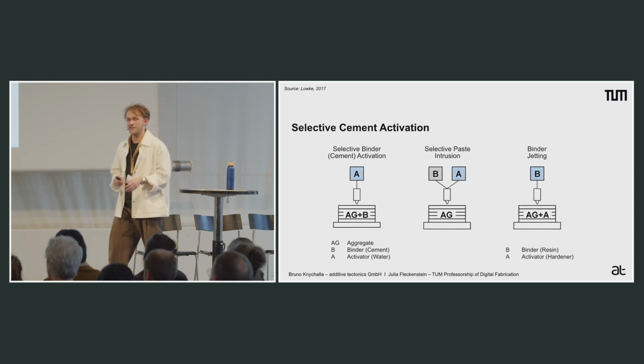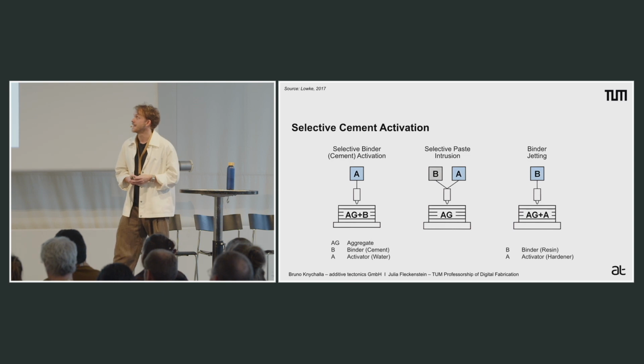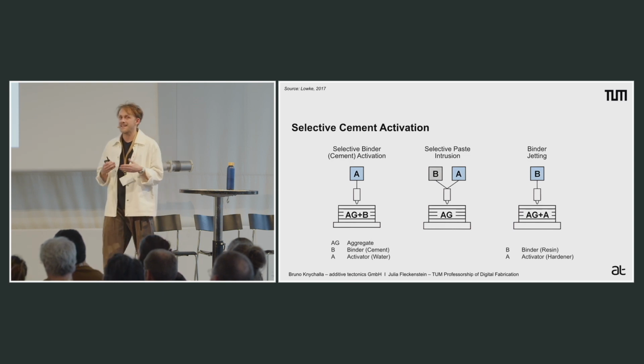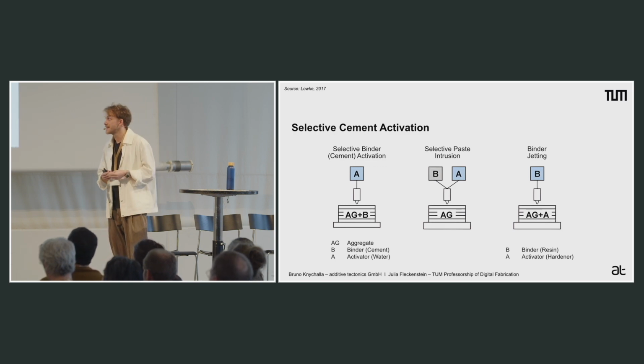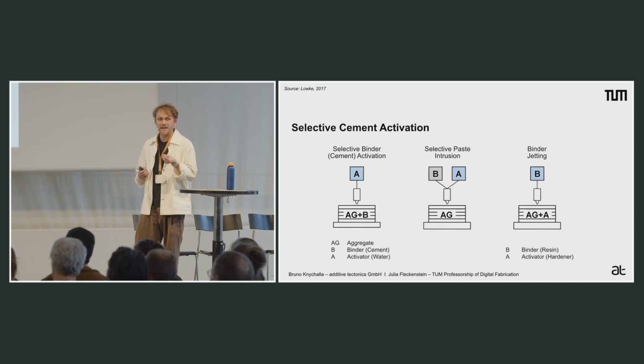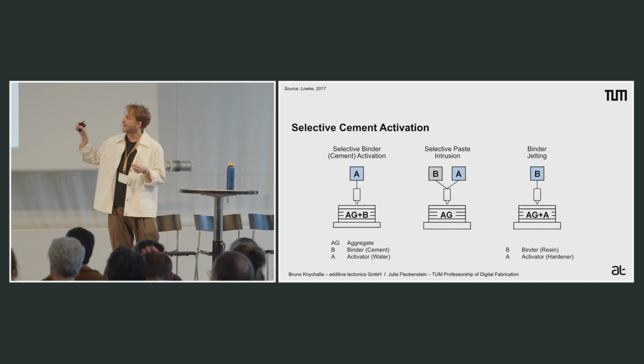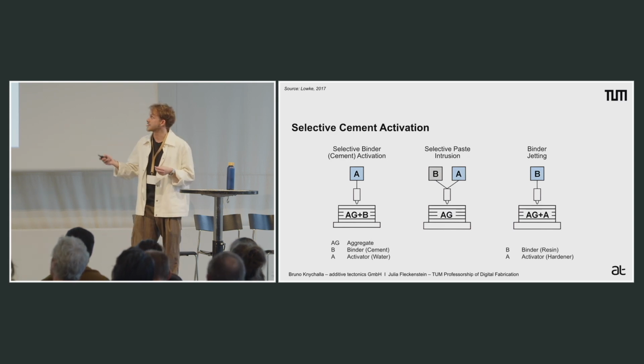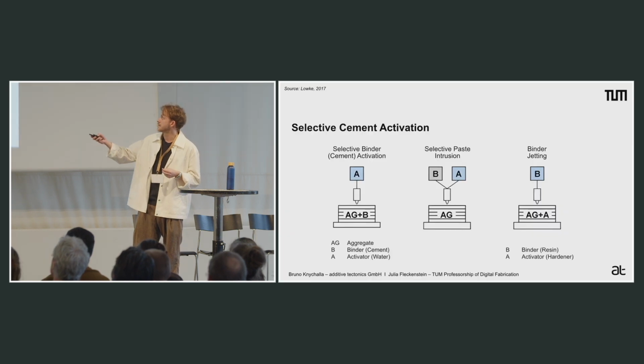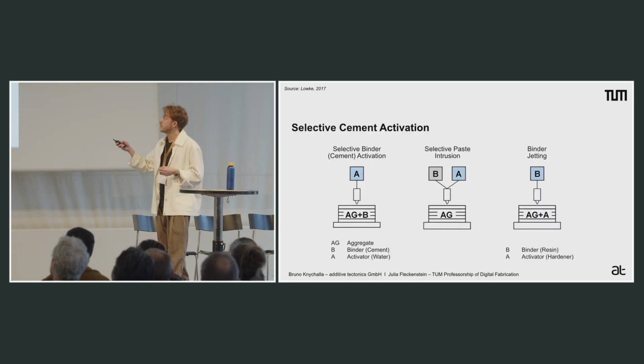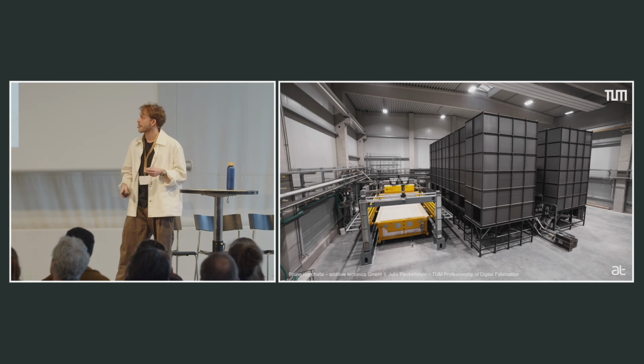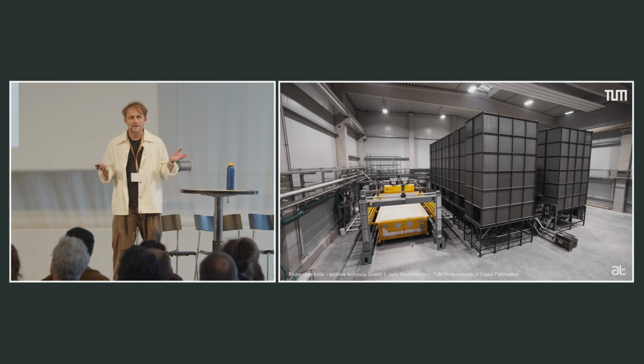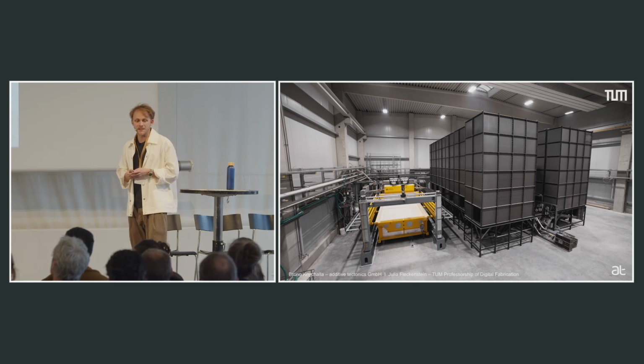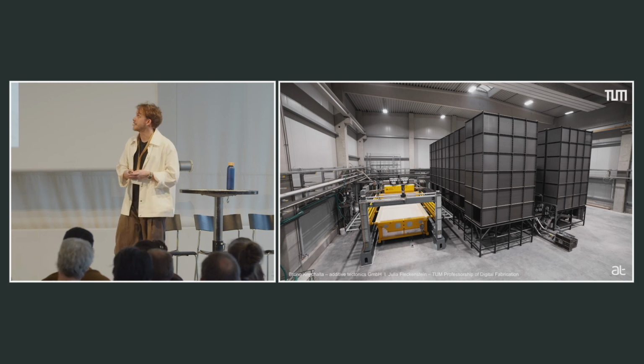Our fabrication technology of choice was selective cement activation. Selective cement activation is a particle bed technology, and it basically jets an activator onto a powder bed. And in the powder bed, there's a cement, basically a dry cement, and the cement hardens. So aggregate and binder are in the powder bed, and just the activator is jetted. Here you see it. While in binder jetting, you basically jet the binder. So this is our big future factory at Additive Tectonics. Here we developed a process.